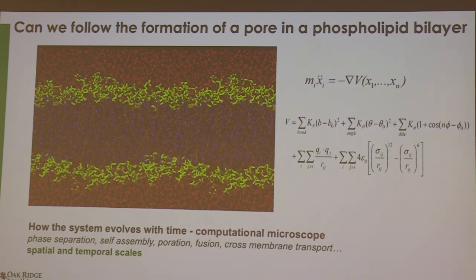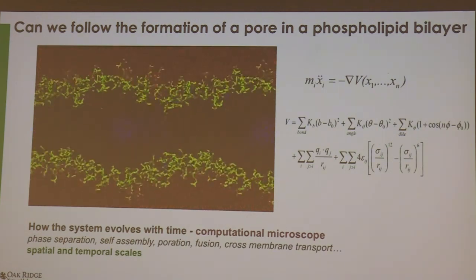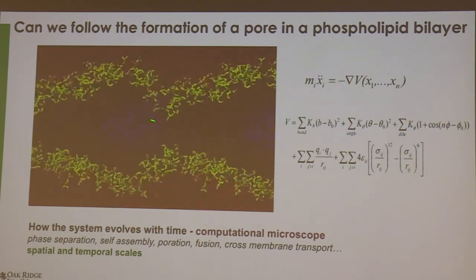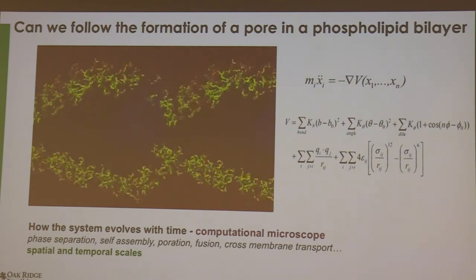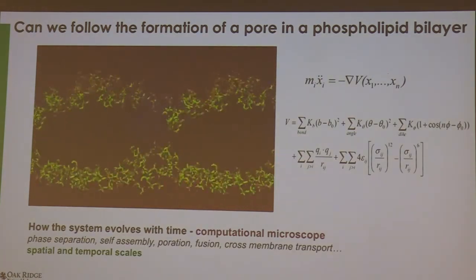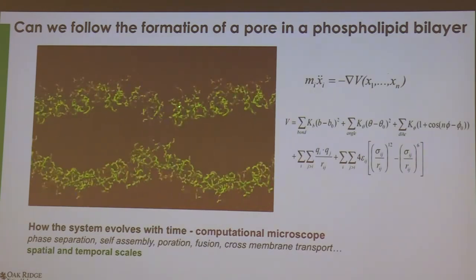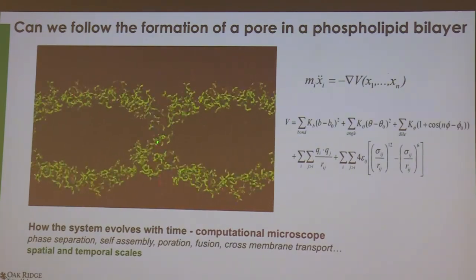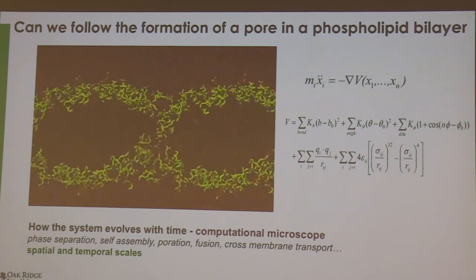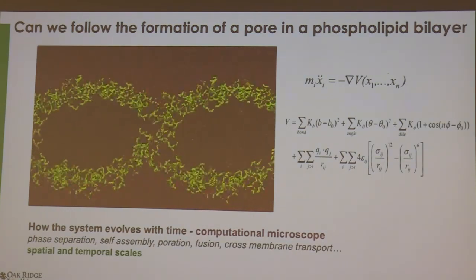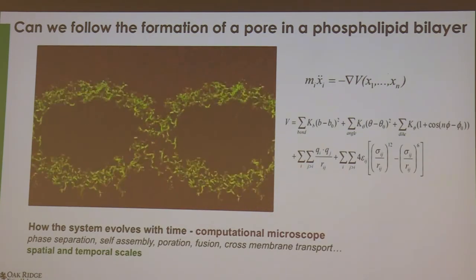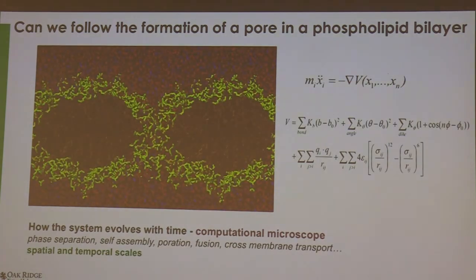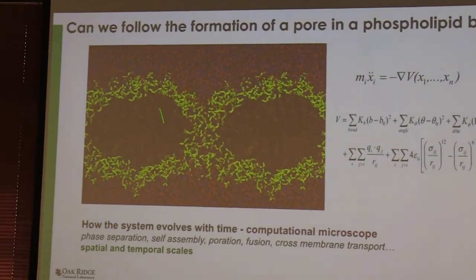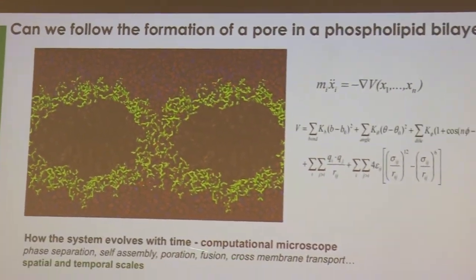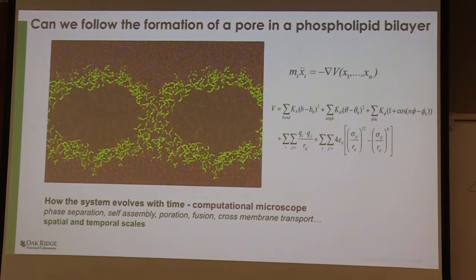Yeah. So as I mentioned, we'll follow it over time. It's a little blurrier than I thought. You can see immediately these phospholipid molecules or lipids are coalescing and forming some interaction with the phosphate, and then they actually form a pore, and then the water goes through the pore. So it actually does porate. That is a really quick microsecond simulation, but now we have a fully stable pore, and the water is permeating through it. So you can get ion transport across that into whatever's down here, which would be the cell. So it matches what we believed would happen. It doesn't always match what we believe would happen.